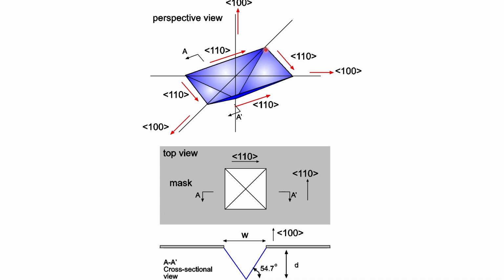Now, if you have a 3D structure like this, where the masks are aligned to 110, you are going to form an inverted cavity. The inverted cavity is bound by 4 111 planes. And if you look at the cross section, the slanting degree is 54.7 degrees.